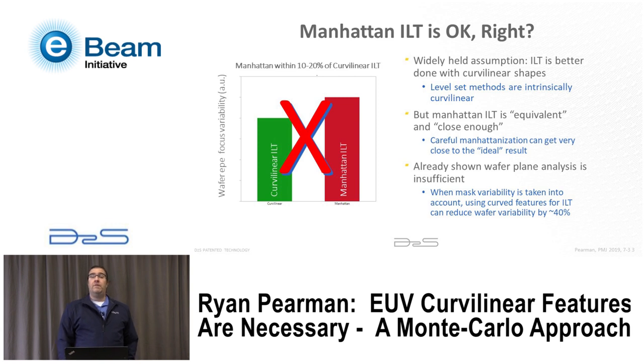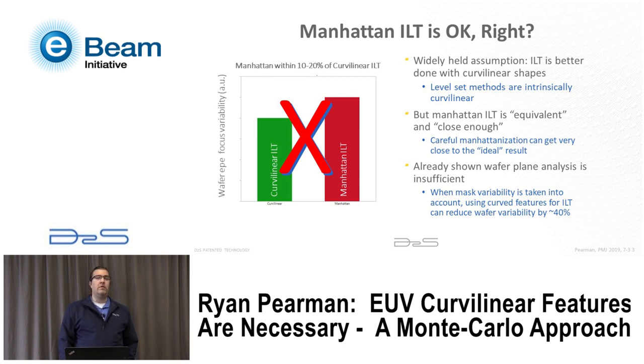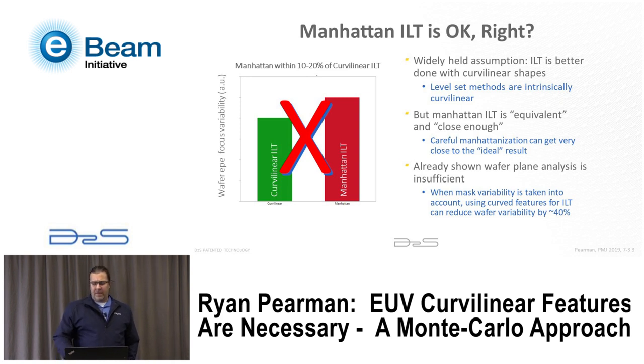Just recently we've done a set of studies first on immersion lithography, and showed that if you take into account the mask variability in addition to the wafer variability, you'll find that you incur about a 40% penalty in the overall process window by staying with Manhattanized features. But that's actually not the end of the story — that's not the reason why we'd want to use curvilinear features for EUV.